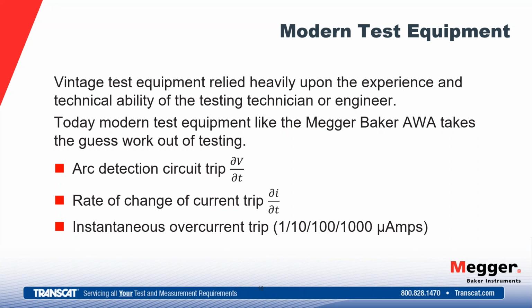Instantaneous overcurrent trip. So it has trip settings and is able to, again, stop the test if at any point it detects an overcurrent. And on the surge test, we also have what we call the pulse-to-pulse EAR. We're looking for wave instability, and if that waveform becomes unstable, it trips the tester and we stop the test at that point. So these safety measures are built into the testing that weren't always there with older equipment.